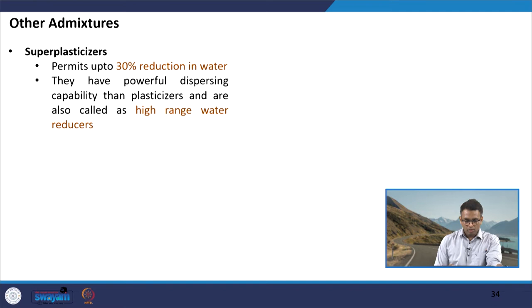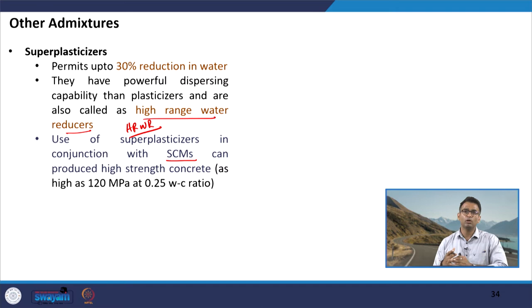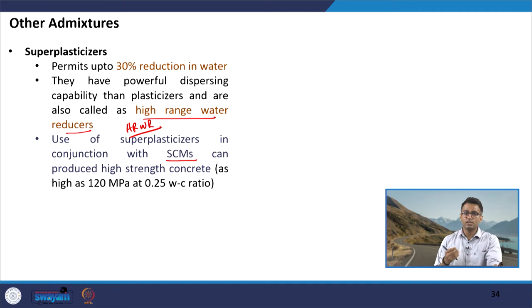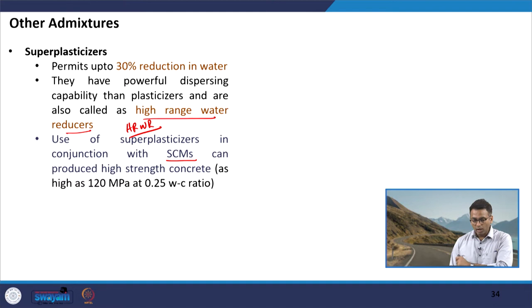Because of their powerful capacity, superplasticizers are also called high range water reducers (HRWR). Superplasticizers also facilitate production of high-strength concrete, especially when used in conjunction with SCMs — supplementary cementitious materials like silica fume, metakaolin, fly ash, GGBFS, or rice husk ash. Silica fume is very fine, increases water demand, and reduces workability but provides high strength. Superplasticizers in those mixtures can maintain workability and allow silica fume to do its work, producing high-strength concrete.